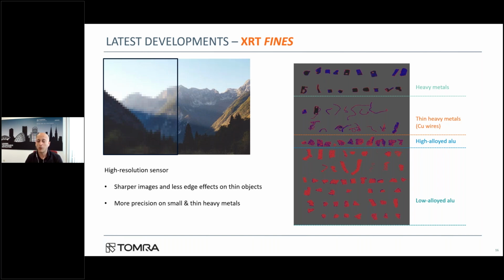So especially for sorting Zorba fines down to 5 millimeter, for example, the higher recovery of heavy metals with this XRT Fine Sorting technology can have really a significant benefit, and it allows the production of an aluminum fraction ready for melting.